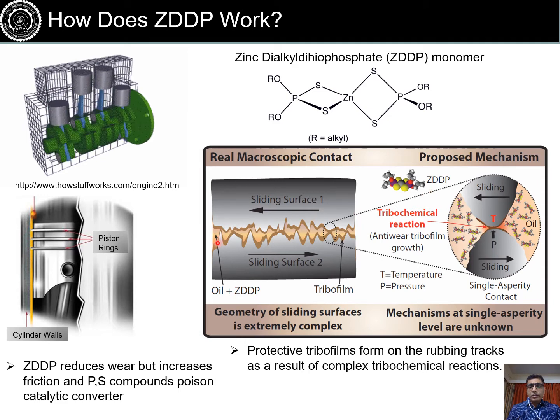And what has been observed is that at the sliding interface, a tightly bound layer is seen, which protects the surfaces. So it acts as a protective layer. And what has been hypothesized is that due to high contact pressure at these small sharp asperities touching each other, at elevated temperatures, and due to shear, some kind of reaction happens in presence of these molecules which results in these films. But there's no direct evidence of how these films grow and what parameters govern the growth of these films, because of the complexity of these macro scale interfaces